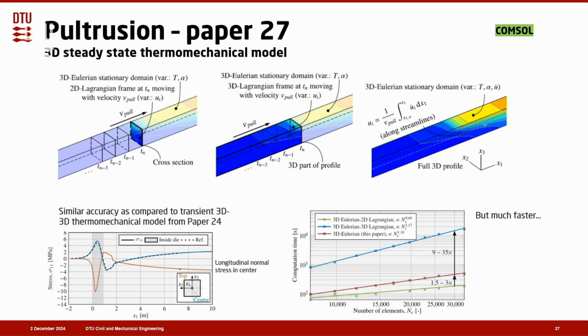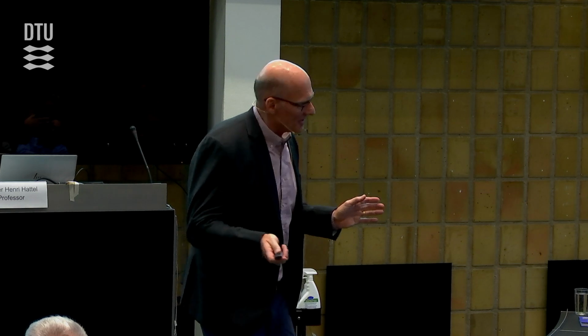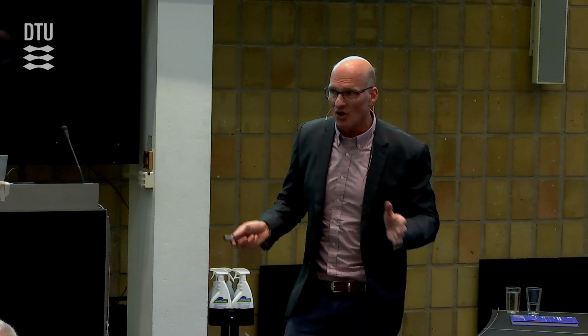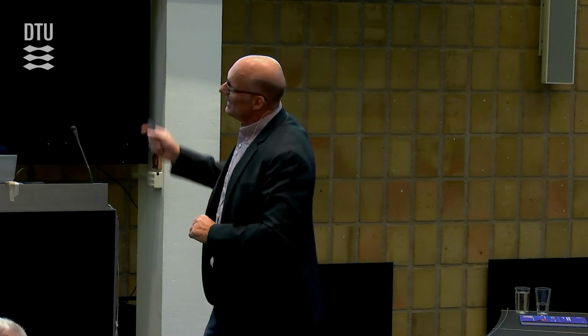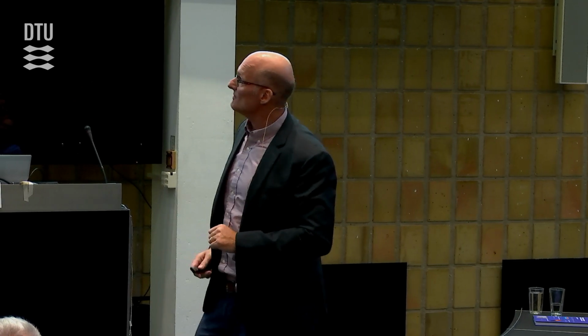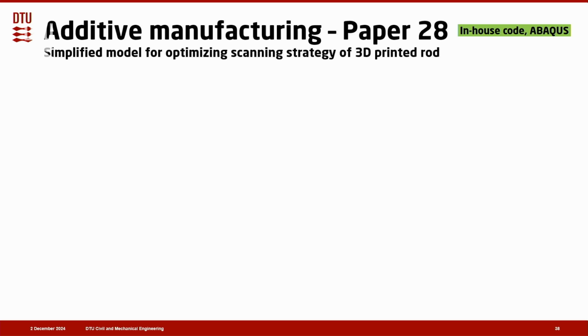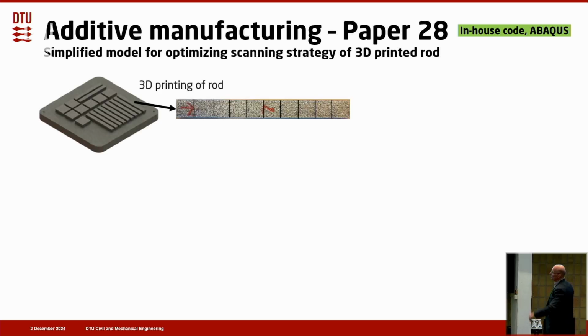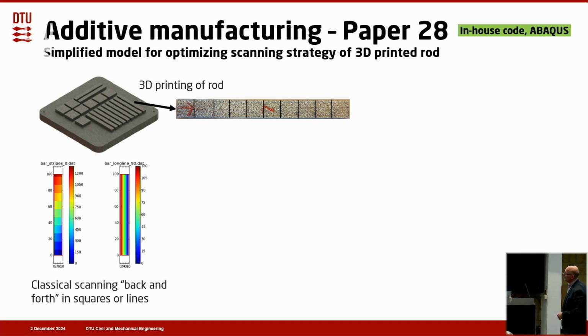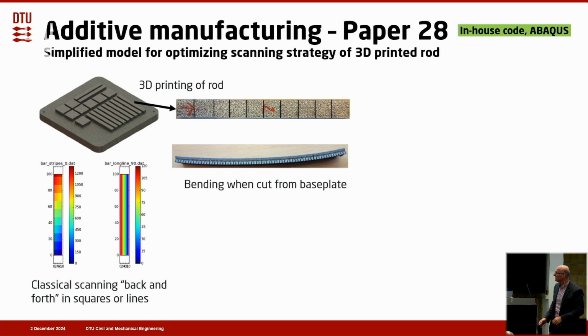Then comes the final group of manufacturing processes, that's additive manufacturing, also known as 3D printing. In the beginning, we made a simplified model for optimizing the scanning strategy of a 3D printed rod. You see, when you 3D print, you have a laser, you melt some material, and then you cut it from the base plate. Now this was scanned in the classical way, back and forth in squares or lines. So you scan, scan, scan, scan, and then you cut it, and how does it look then? It looks like this. It bends when it's cut from the base plate. So that is, of course, a problem.